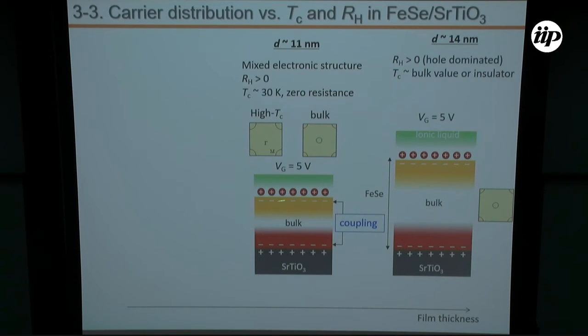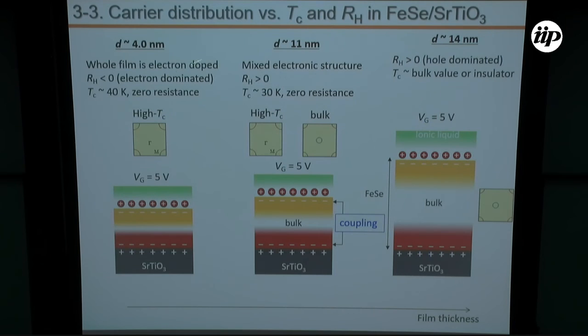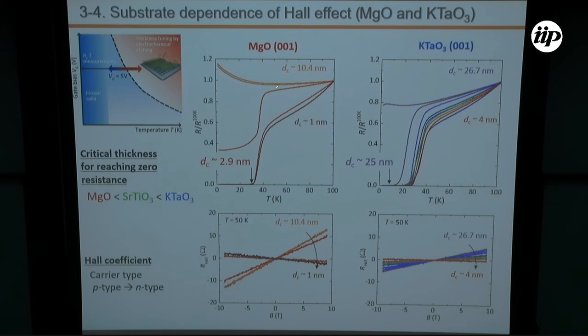But still in between, there are hole regions, resulting in a very small Hall coefficient with small slopes. And finally, in the thinning below 4 nanometers, the electron-rich layer covers all samples. In this case, high TC superconductivity with negative Hall coefficient occurs. And a similar trend is also observed for MgO and potassium tantalate, with the appearance of high TC superconductivity followed by the sign change of the Hall coefficient.